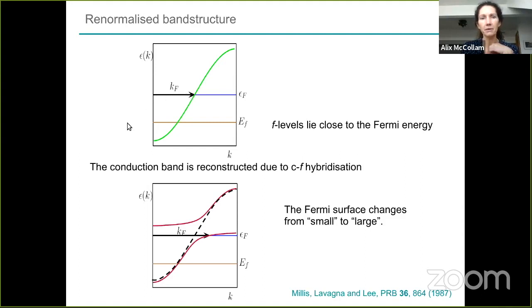When you have the interaction, or when the Kondo singlets form, or when you have a strong Kondo interaction, the conduction band is renormalized, or it reconstructs due to this hybridization. This green one here would be the conduction band, and here it would change into the red bands. The Fermi surface would become larger, so the Fermi wave vector would extend. The band structure becomes flatter here at the Fermi energy, so you get an increase in the effective mass associated with that particular band, and you have a large Fermi surface.